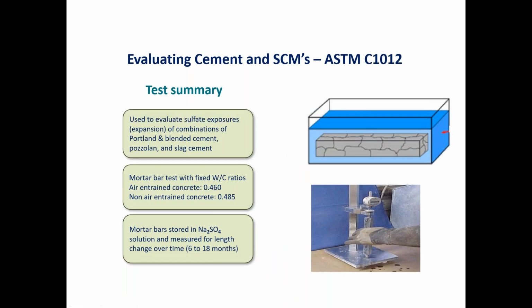So to understand how we can quantify our risk of sulfate attack, and knowing that sulfate attack is pretty much exclusively in the paste portion of our concrete, and a very high amount of this relies upon the cement itself, we'll look at the method of evaluating sulfate expansion potential or sulfate reaction potential, and that standard is ASTM C1012.